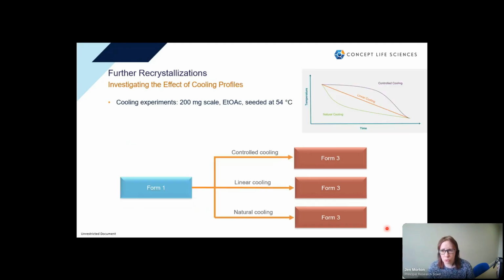We then went on to investigate the effect of the cooling profile. We took form 1 and we employed 3 different cooling profiles. So our original antisolvent recrystallization was probably running pretty close to a natural cooling profile where you have a steep ramp at the beginning. Crystal16 uses a linear cooling ramp, and controlled cooling is something you hear about quite often in terms of recrystallization, where you have a very shallow ramp to start with and then it tails down later. So we ran experiments with each of those 3 profiles, and again we obtained form 3 from all of those experiments.